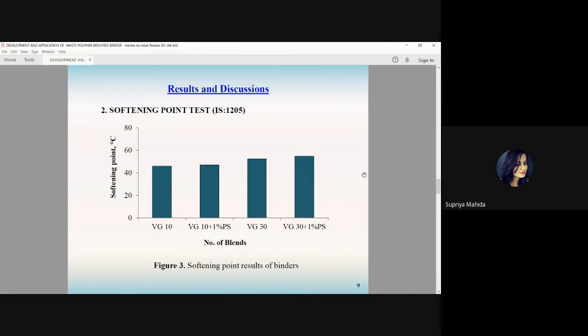The softening point we proceeded with according to IS 1205, which says at what temperature the binder will soften. So here, when we add thermocol in conventional bitumen, the softening point gradually increases. It increases by a small amount. That means there is some property by which it resists softening at temperature. Because bitumen is a temperature-susceptible material, we want a hardened material and, at the same time, a softened material. So the softening point is increasing after adding thermocol waste in the conventional binder.